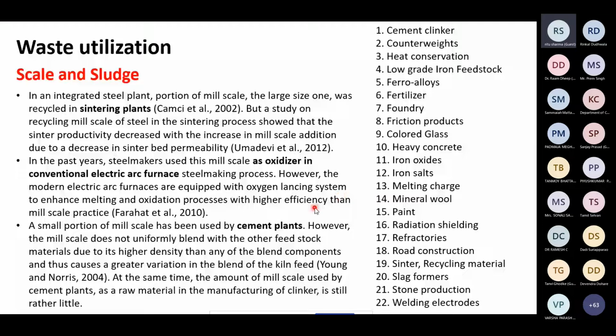So now in electric arc furnace, what happened is that we require a continuous supply of oxygen, and the modern electric arc furnace uses the oxygen lancing system. The oxygen lancing system supplies enough, well-calculated stoichiometric oxygen to the electric arc furnace, so that further oxidation of the metal does not happen. That's why the utilization of mill scale in electric arc furnace is reduced.